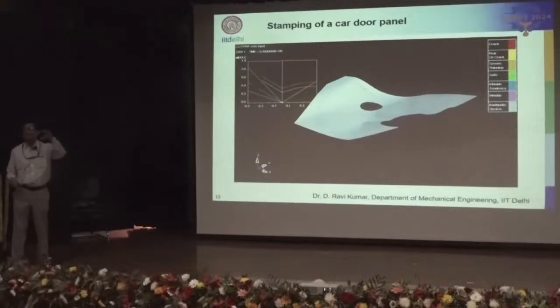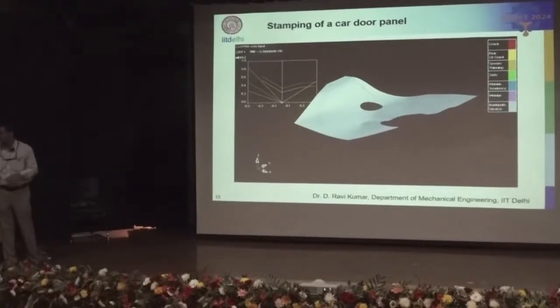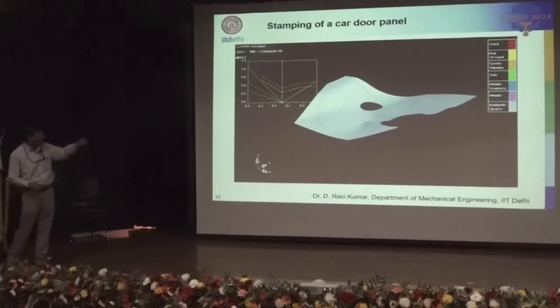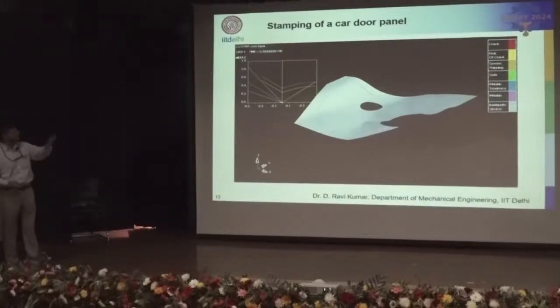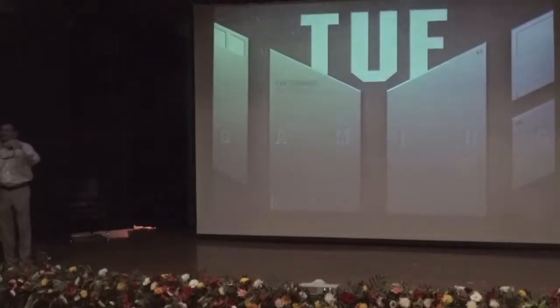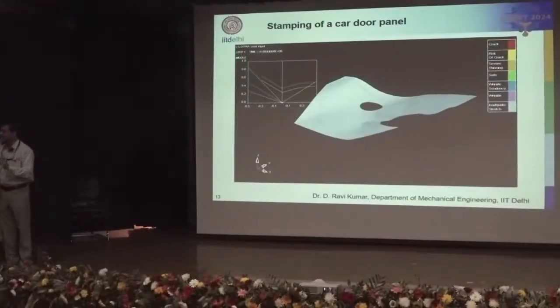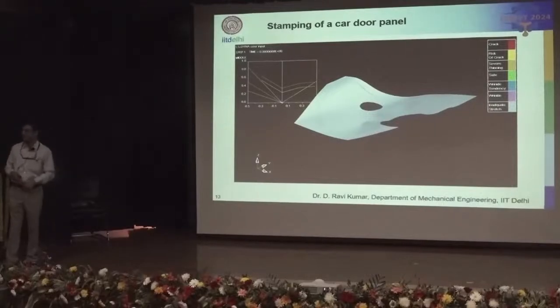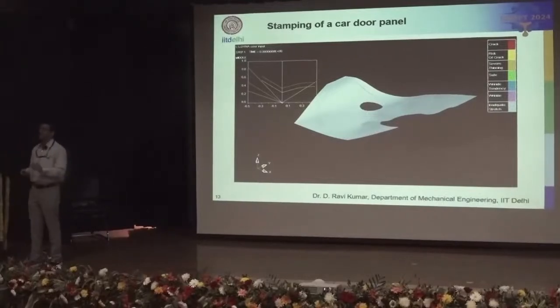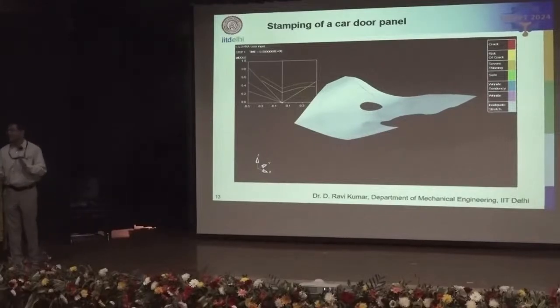So this is stamping of a car door panel in the finite element simulation. And you can see on the left hand side corner the forming limit curve of the material. And the strains predicted from this simulation are directly superimposed on the forming limit curve. And if they're exceeding the limit, then it indicates failure. So we need to rework on the variables so that we can take the remedial action. So in this way, the formability analysis, either by experiments or by simulations, is extremely important to predict failure and also to diagnose failures.